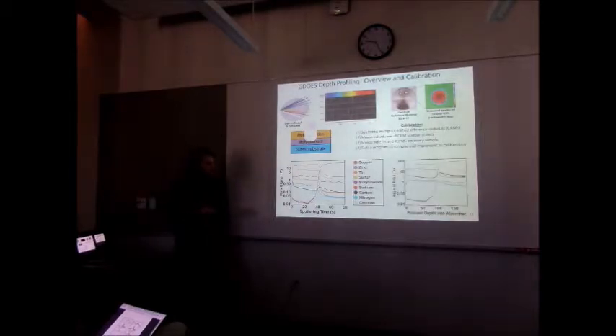So I use a pretty elaborate calibration procedure to make this data a little more meaningful, where I use certified reference materials, integrated the volume of sputtering, did EDX and ICP-MS, and this allowed me to find the atomic fraction as a function of depth for these different films, for both the precursor and the selenized films. This let me get a ton of data, which is really rich, and if you want the full details, you're going to have to read the paper, because I don't have any time to discuss all of this. But I'm just going to hone in on one thing related to this impurity layer.